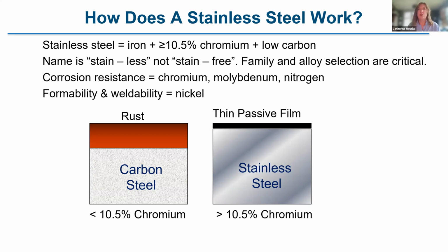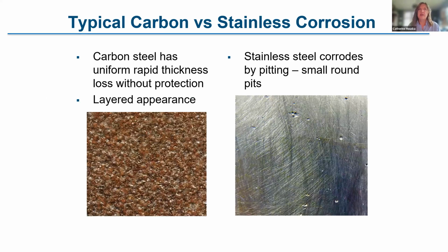In comparison, carbon steel forms rust on the surface, a thick uniform layer. When stainless steel starts to corrode, we get little pits on the surface. I've cleaned the sample to clean away the staining that was on the surface so you could see what that looks like. In comparison, carbon steel has uniform corrosion over the surface and a layered appearance. If it's not removed, that layered area can actually accumulate more of what's corrosive in the surface and moisture and accelerate the corrosion process.